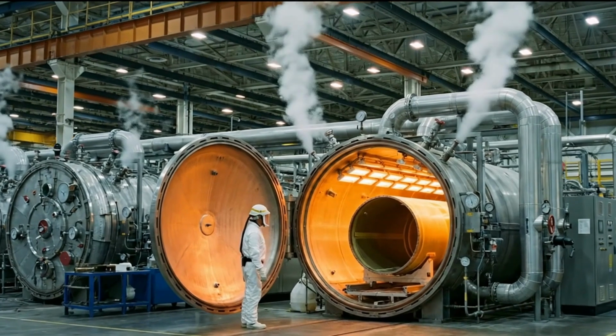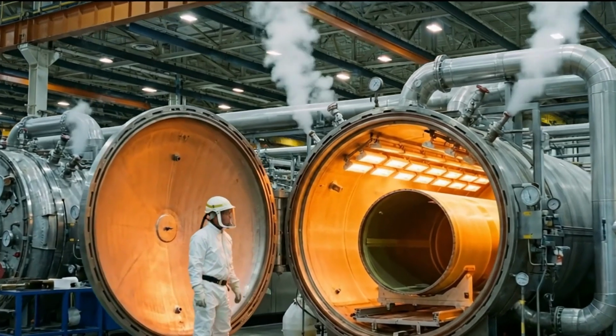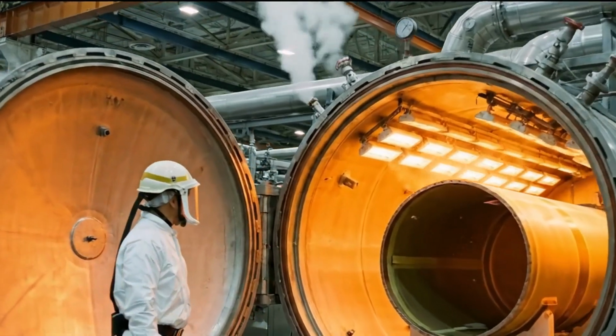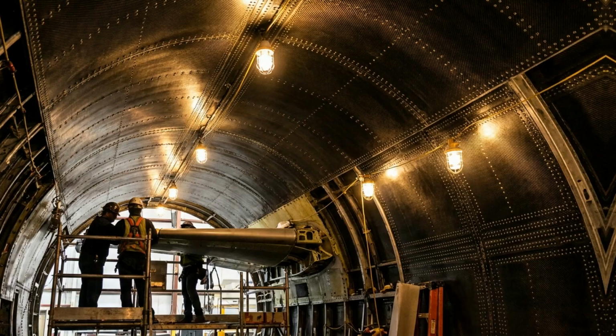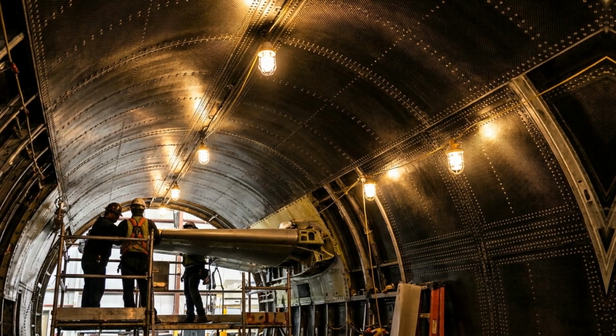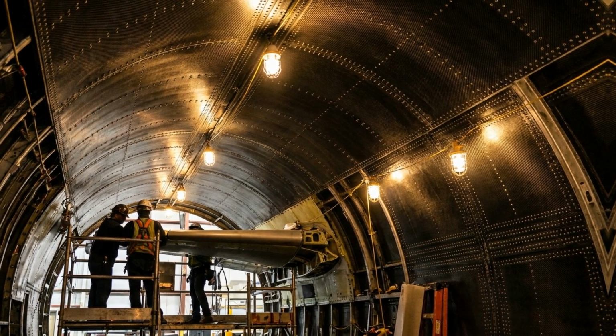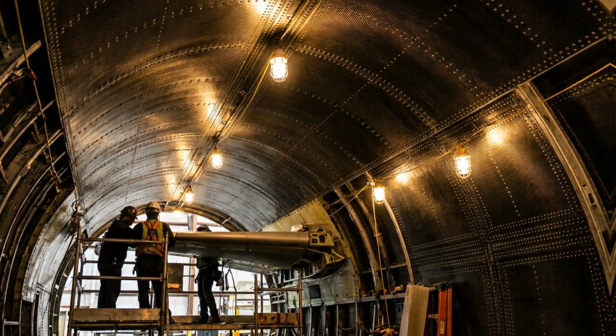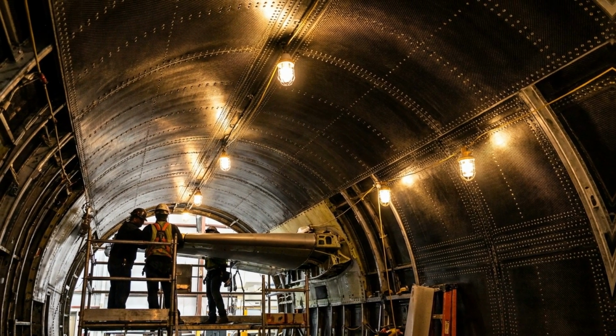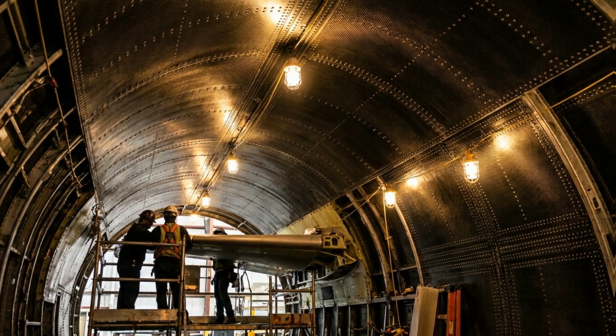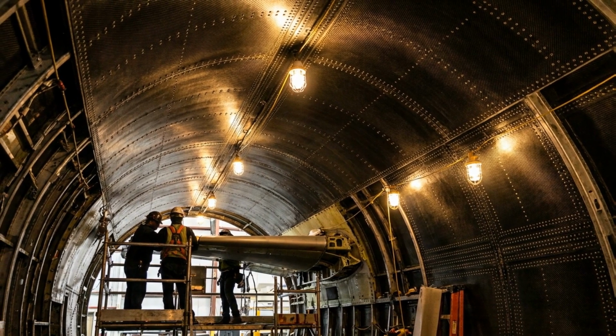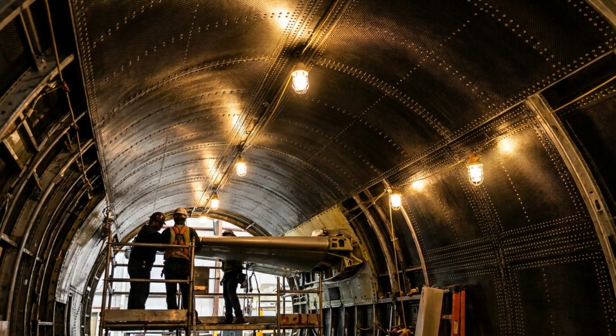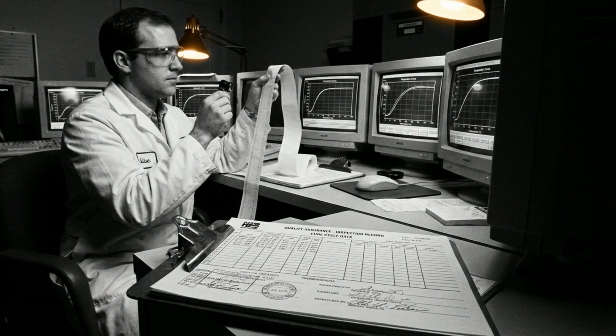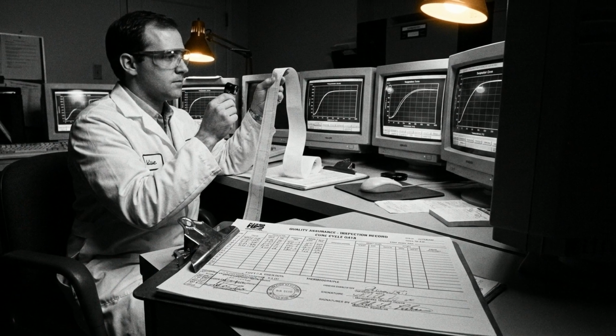The autoclave that cures a 787 fuselage barrel is processing a component that will eventually carry 240 passengers at 40,000 feet, pressurized to the equivalent of 6,000 feet altitude for the operational life of the aircraft, potentially 30 years of pressurization cycles. The structural integrity of that barrel depends on a cure that happened correctly, years earlier, inside a pressure vessel in a manufacturing facility.